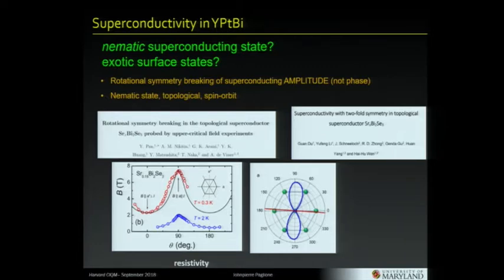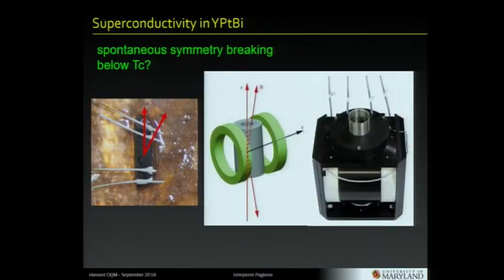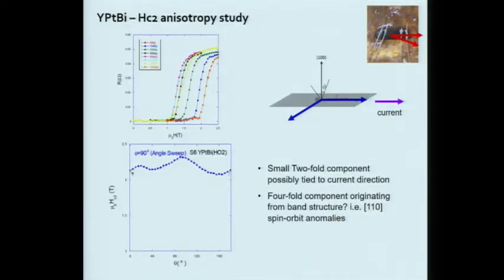So we asked the same question: can we see something like this in yttrium platinum bismuth by looking at, for instance, HC2 as we rotate around? So we started to do this experiment. Here's a crystal, for example. We have a vector magnet, so we fire that up and start doing experiments. We found something very peculiar. So here's the first experiment, which is just a crystal where we rotate the magnetic field from parallel to the current direction to perpendicular, but it's always in the plane of this crystal, like that.